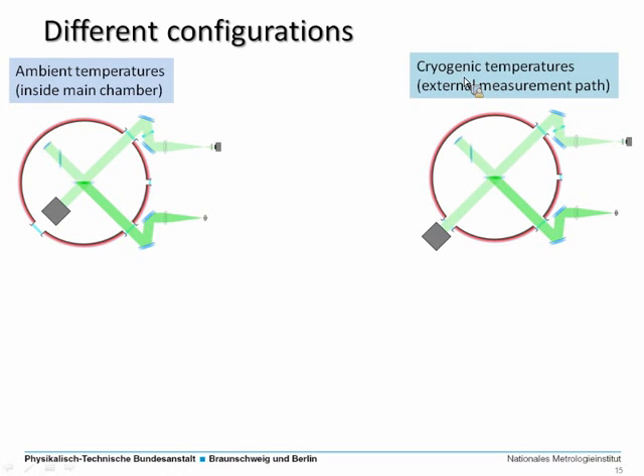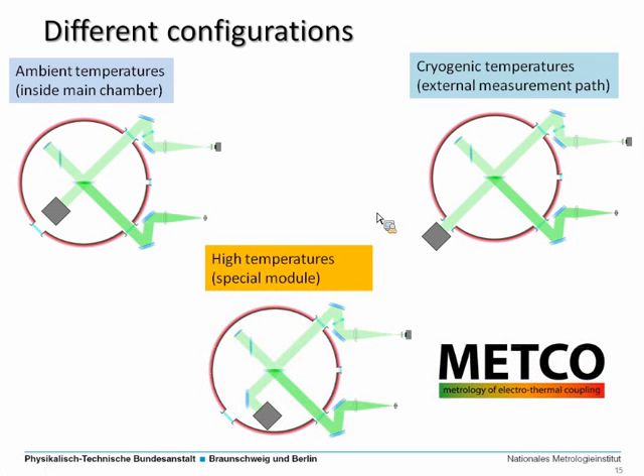And we also have developed in the past years a measurement path, which is an external module for measurements at cryogenic temperatures, starting at 7 Kelvin and then up to ambient temperature. This is already working. And what you will see in the next talk of Tatiana is the newly developed module for measurements at higher temperatures up to 200 degrees Celsius. I don't want to tell too much about this because you will see more details in the next talk.